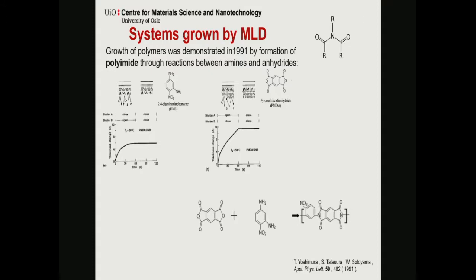This is something that I anticipate that you're going to see for most of your systems in the future as well. Some chemistries go in there. There are numerous reasons why. This here is claimed to be some physisorption. Okay, you could get rid of that additional physisorption step by increasing the temperature up to 80 degrees. So then it looks very nicely.